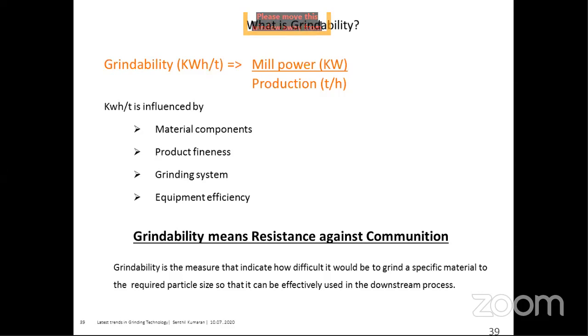Wherein when we see this, the ball mill consumes much higher power than that of the vertical roller mill and the roller press. Because in the ball mill, the whole mill rotates, and it has to carry the weight of the balls and the material, and it generates more heat. Most of the energy we spend for the ball mill will be used for generating heat, which we may not need. So efficiency wise, the ball mill is less efficient than the vertical grinding. Typically, when a ball mill consumes 100 kilowatt, the vertical mill consumes only 55 kilowatt. That is, the vertical roller mills are 45% more energy efficient than the ball mill.